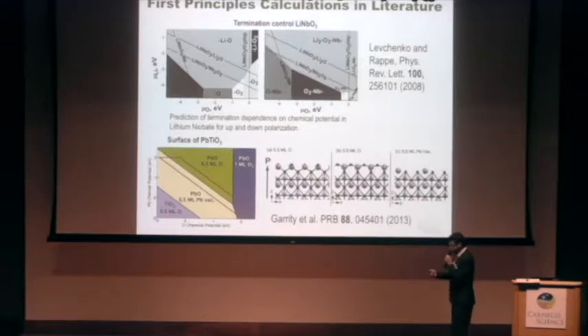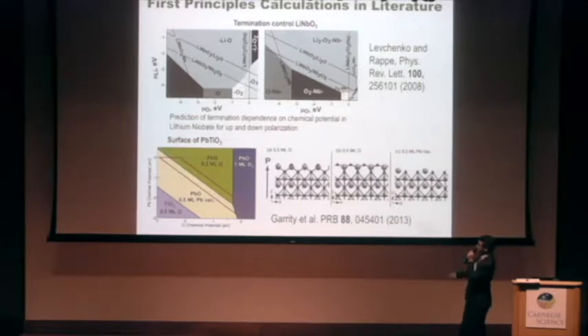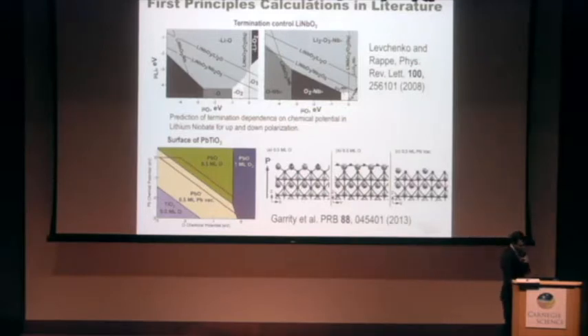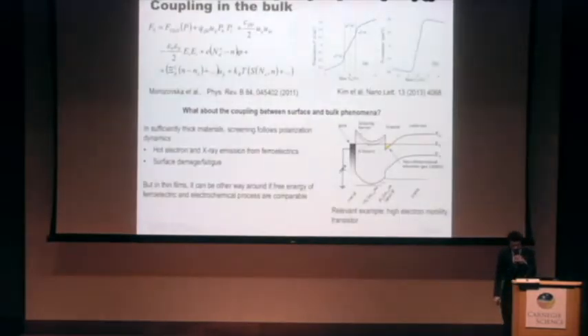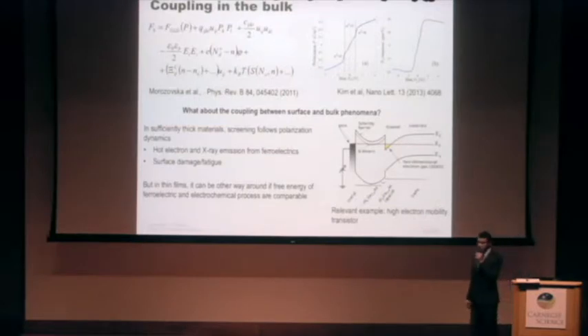I'll just point you to one work here with lithium niobate. Obviously you have a very complicated phase diagram depending on the electrochemical potentials involved. But the gist of it is that if you don't have screening from external charges, your surface should reconstruct, and this reconstruction is going to depend on the polarization orientation. That's what's shown in these two studies, in this case for lithium niobate, in this case for lead titanate.